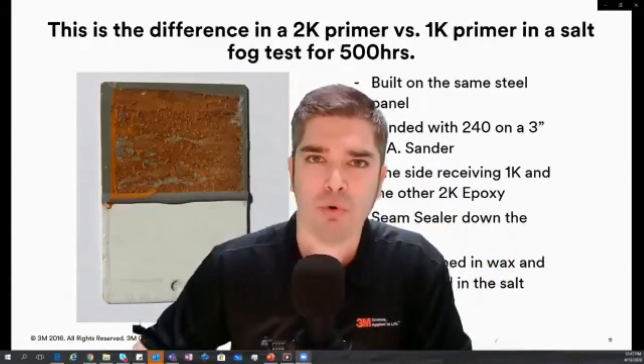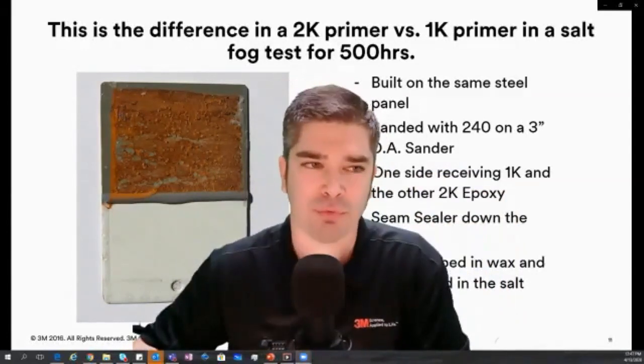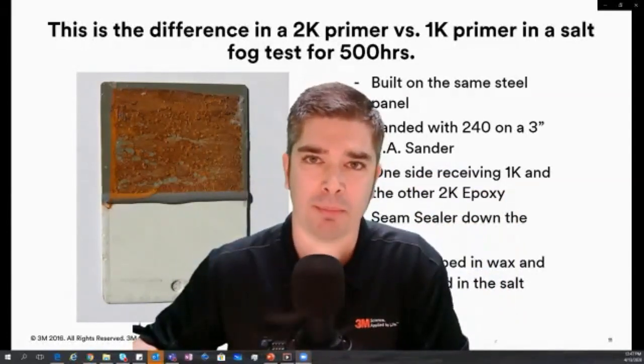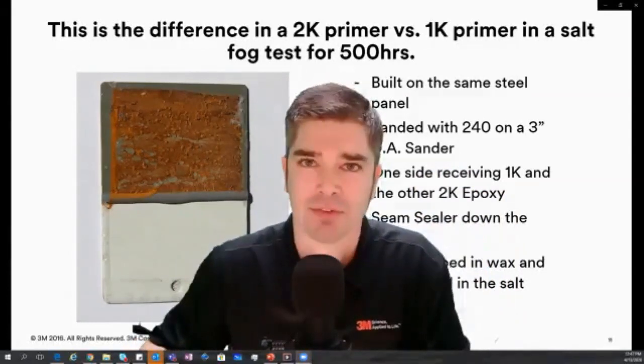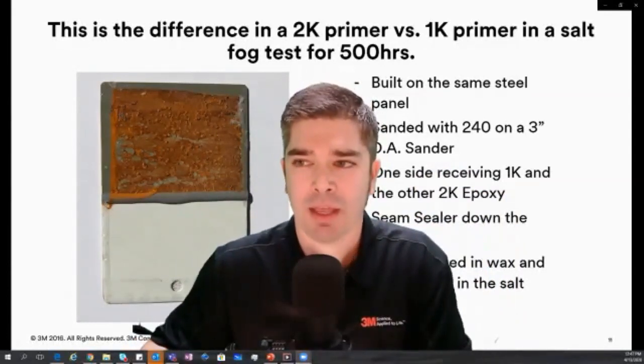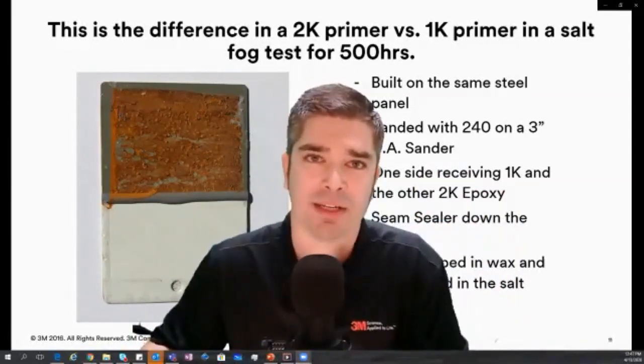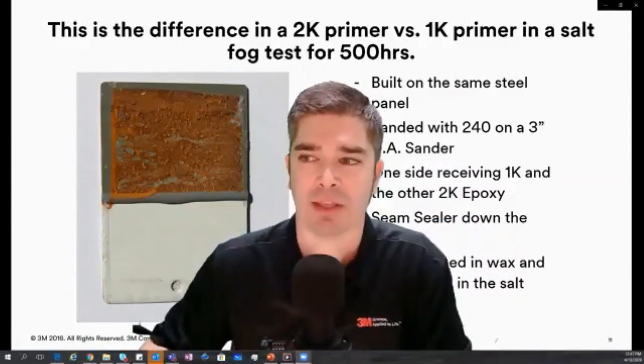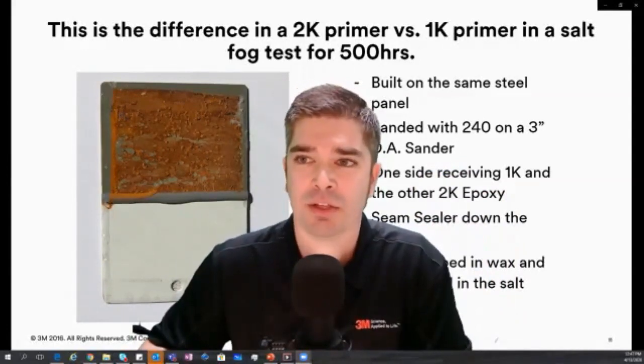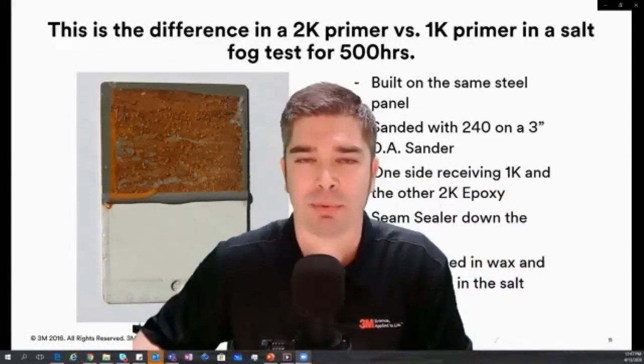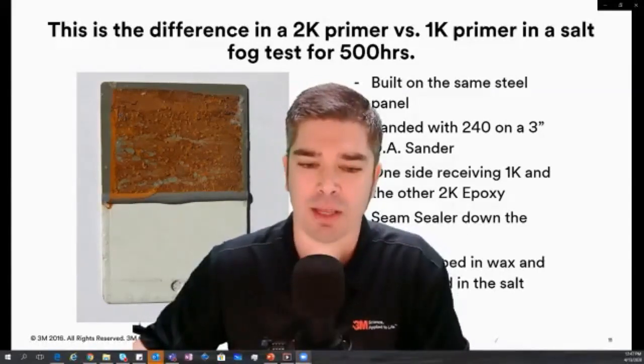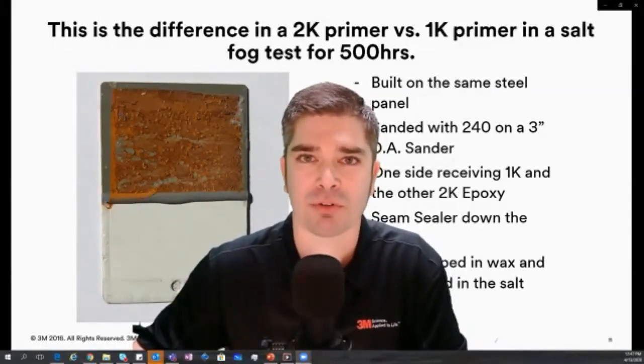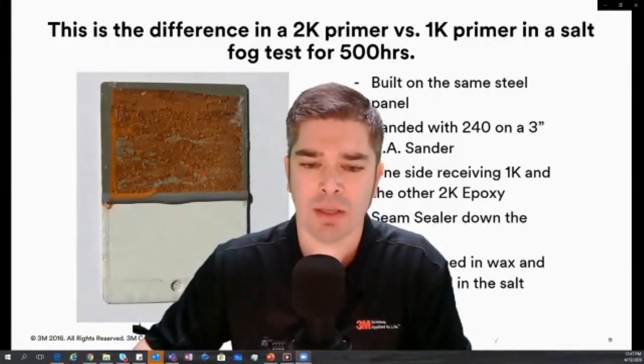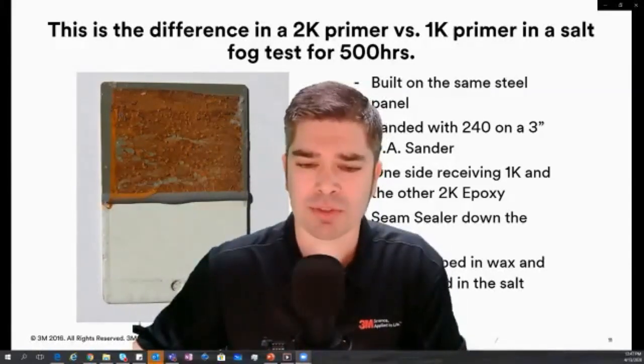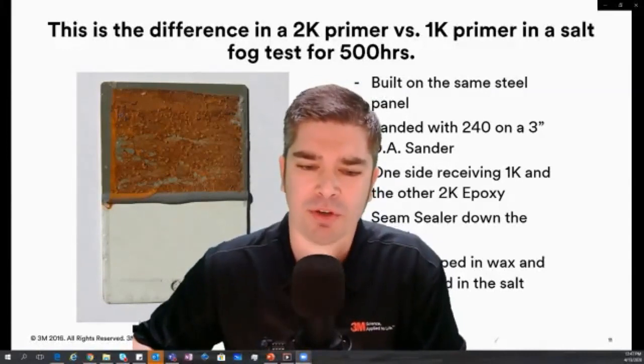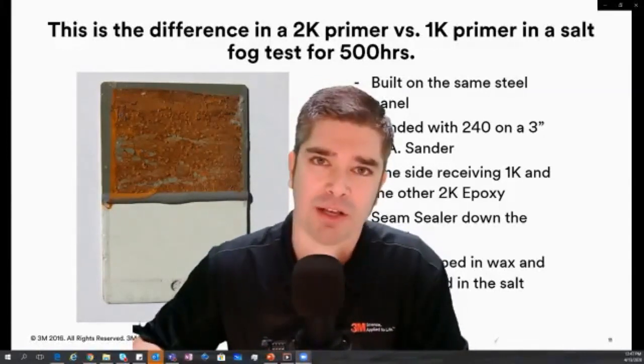And overwhelmingly, we run these tests quite frequently, and we let technicians build them. And we've even had some other outside technicians that have been through our program go back to their shops and try to build a panel in their own way and send it in. And we've put it through our salt tanks and been able to prove that it really comes down to the value of the product. And in this case here, a 2K epoxy primer is going to be the most corrosion resistant primer to be used. Not saying that a urethane can't be used, but with an epoxy, you don't need to put down the acid etch primer first.